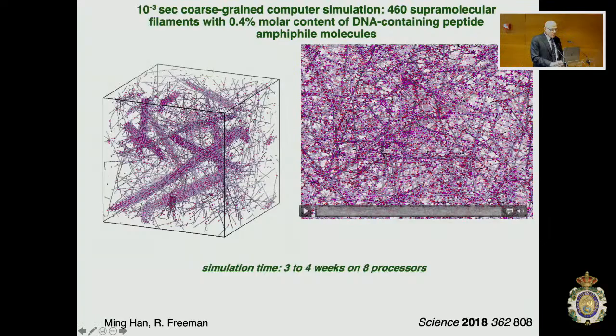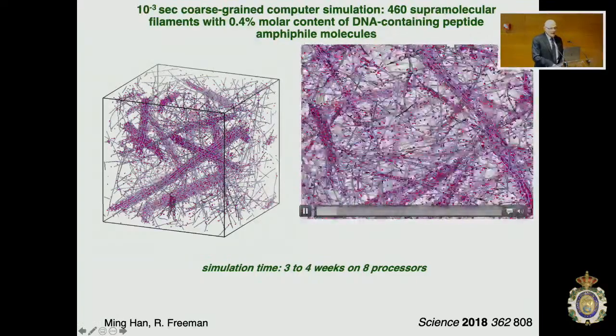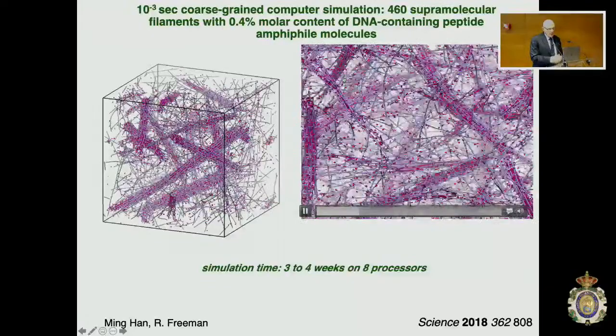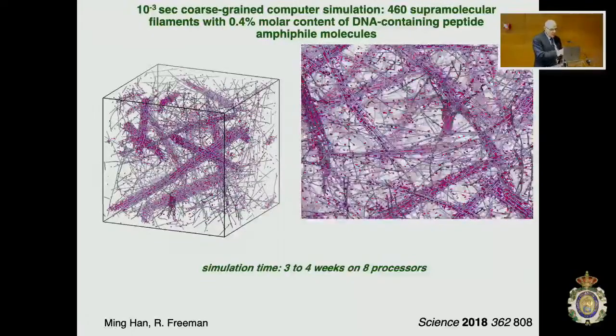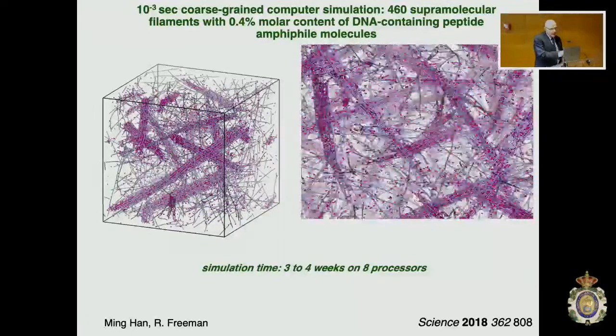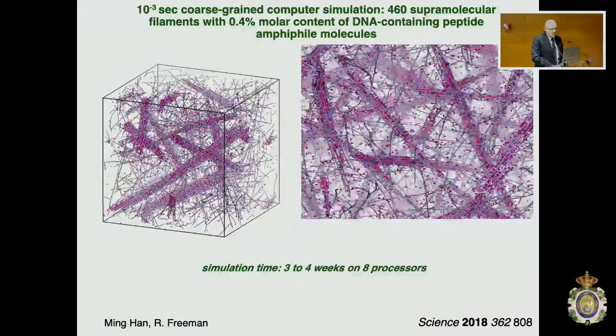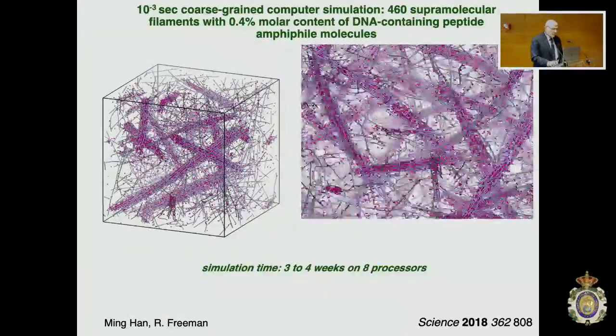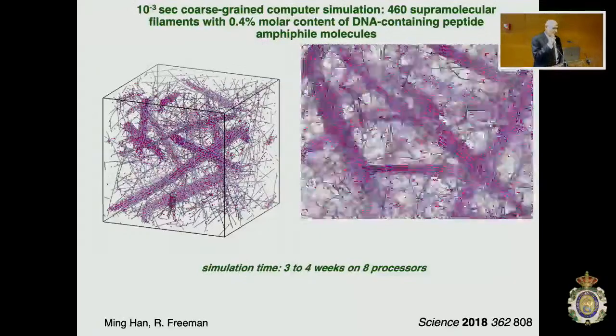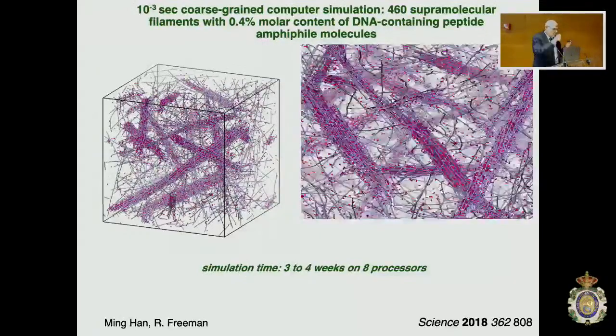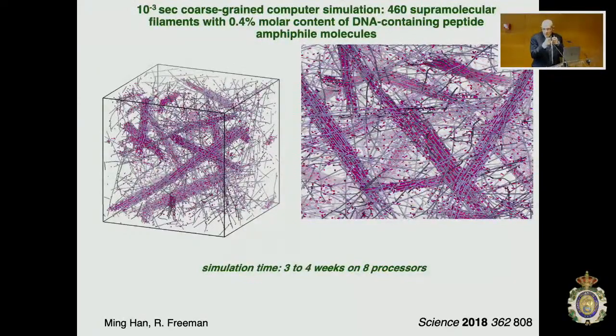And if you don't allow the molecules to escape, you would not see these bundles. But if you allow them to escape, then this is just a larger view of the assemblies. You can do that in the simulation just by putting in your force field a strong cohesive force, and so they cannot walk away. If they walk away, they make bundles. If they don't walk away, they don't.